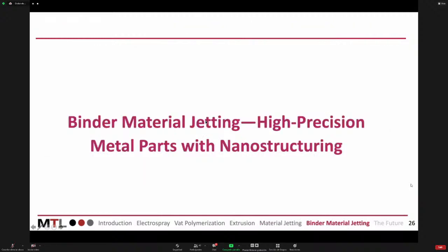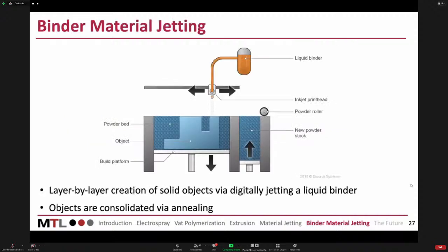Let me shift gears and tell you about the last technology, which is 3D printing using binder material jetting. And the idea is a lot simpler than material jetting. So you have a base material that is a powder, and then you have this inkjet to spray like glue. It's a glue that eventually you can remove. And the technical term would be binder. And as you print these layers, then you put more material, you planarize it, and then you continue building.